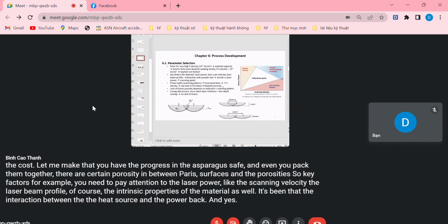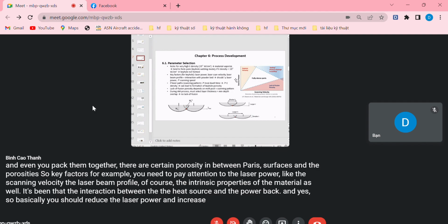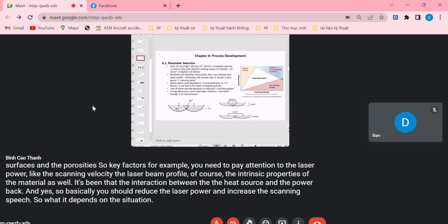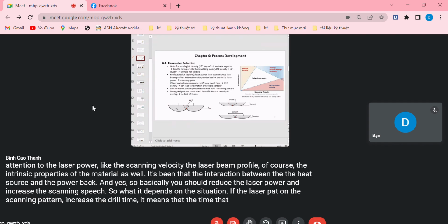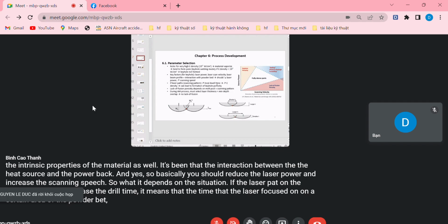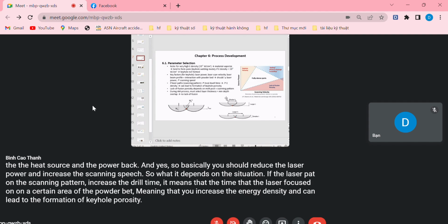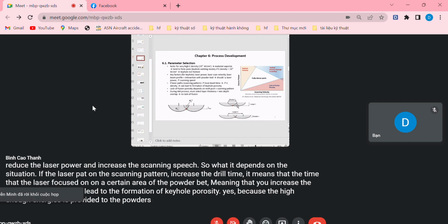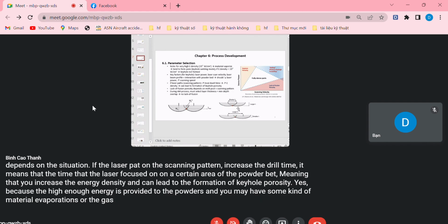So basically you should reduce the laser power and increase the scanning speed. Should, but it depends on the situation. If the laser path or scanning pattern increases the dwell time, meaning the time that the laser focuses on a certain area of the powder bed, this increases the energy density and can lead to the formation of keyhole porosity. This happens because high enough energy is provided to the powders, and you may have some material evaporation or gas pressure, which induces the keyhole effect at that position.